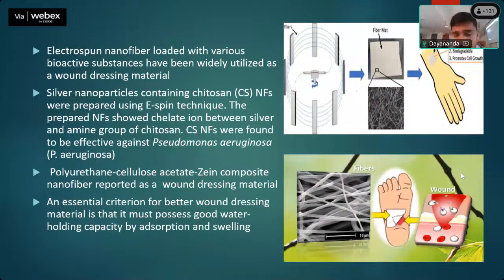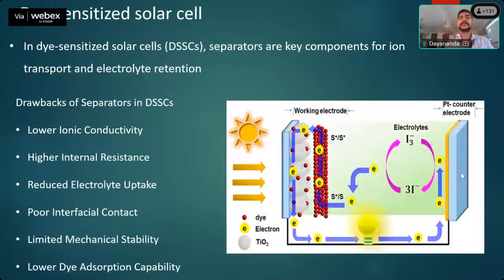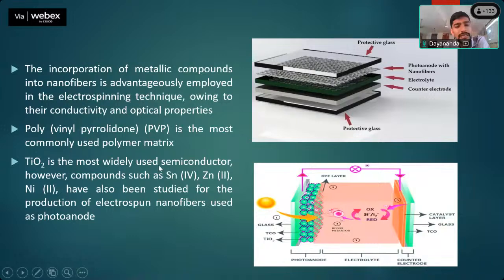In dye-sensitized solar cells, we have a photoanode, an electrolyte, and a cathode. The general issues involved in conventional DSCs are low ionic conductivity and higher internal resistance, among other issues. Incorporation of metallic compounds into nanofibers is advantageously employed in electrospinning, owing to their conductivity and optical properties. Polyvinylidene fluoride and polyvinyl pyrrolidone are the most commonly used polymer matrices, and titanium dioxide is the most widely used semiconductor. However, compounds such as tin, zinc, and nickel have also been studied for producing electrospun nanofibers.